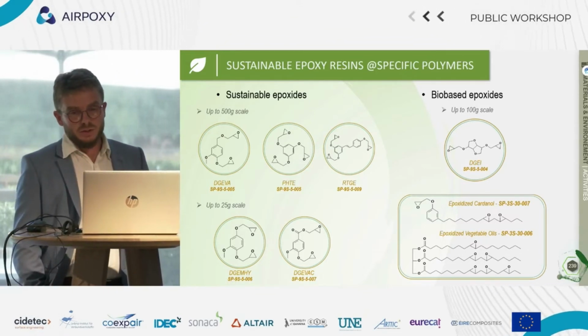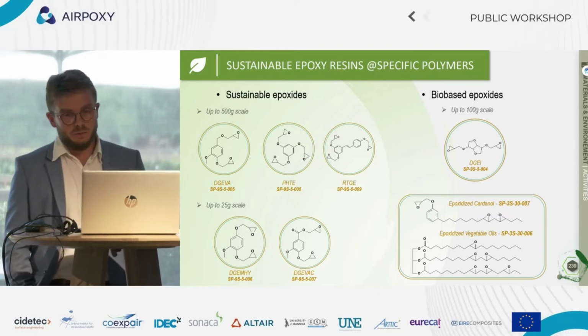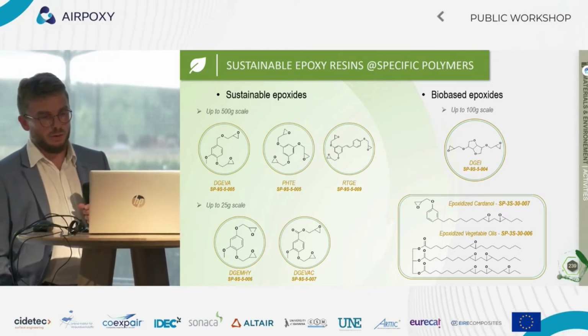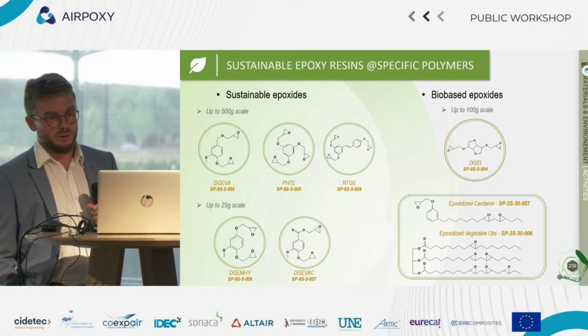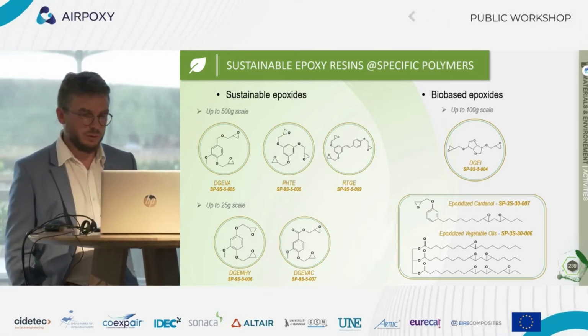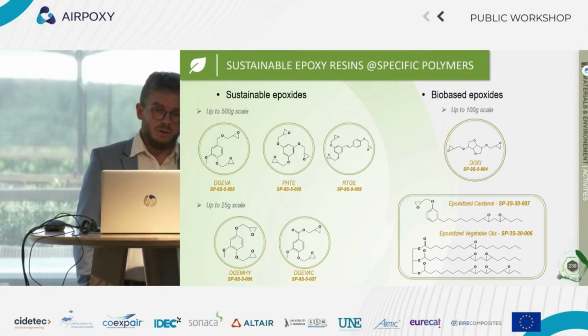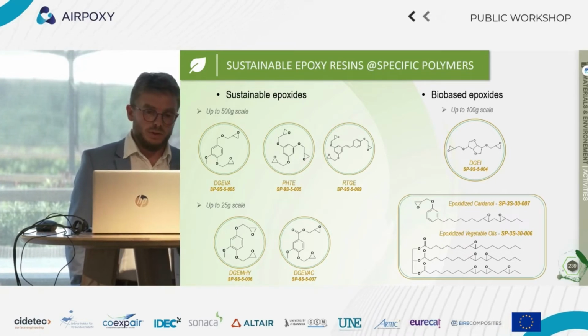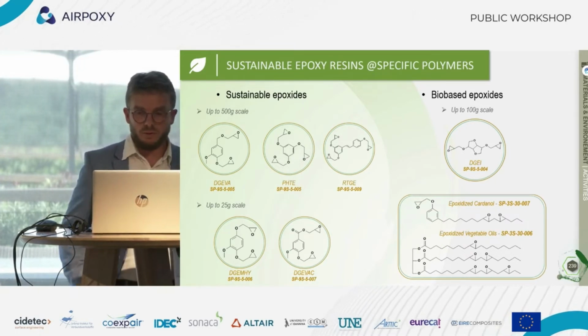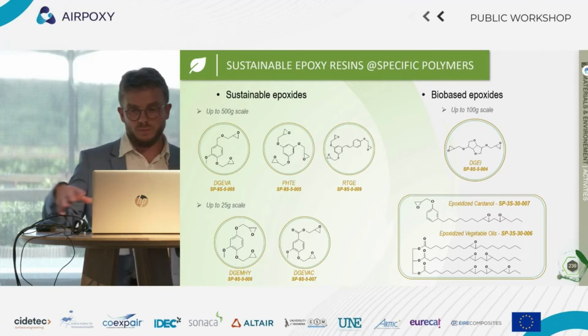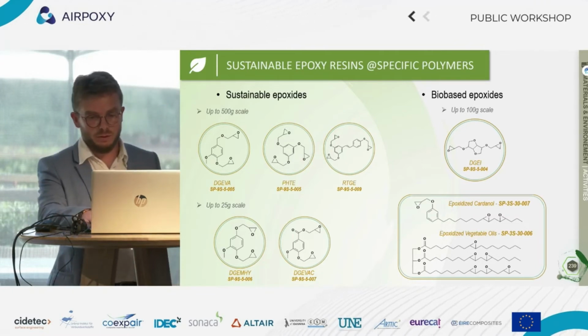We are increasing the epoxy content to increase the mechanical properties, and we have done a huge work on epoxy vegetable oils in the scope of one previous project called AIRPOXY, in which we were able to design epoxy vegetable oil with very different content of epoxy, resulting from the different content in unsaturation.